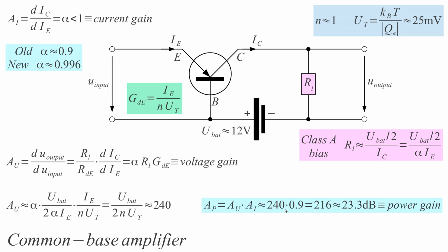I get 240 of voltage gain, and I have 0.9 for current gain, so in total I have 216 times the power. This is 23 dB. So this is quite a useful gain, and this was in fact the way the first transistor was being used, the first transistor that had a very poor alpha coefficient. Now, better transistors were made quite soon from silicon, and planar technology was used for silicon, so manufacturing could be handled much more easily in silicon.